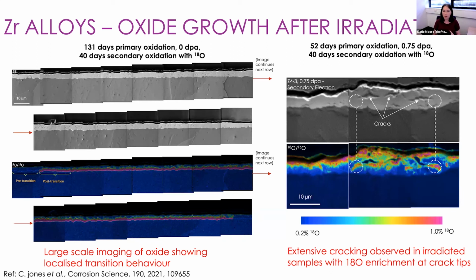If we look at samples in the TEM or atom probe, we may be able to see structural differences or slight compositional differences, but with the isotope, it's very, very clear over large areas of the sample exactly where the oxidation is happening at any particular time point. Now, over on the right-hand side, this is what we really set out to do, which was to look at the effect of oxygen incorporation after irradiation.